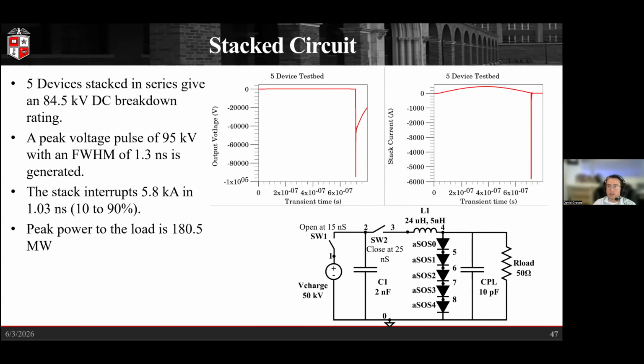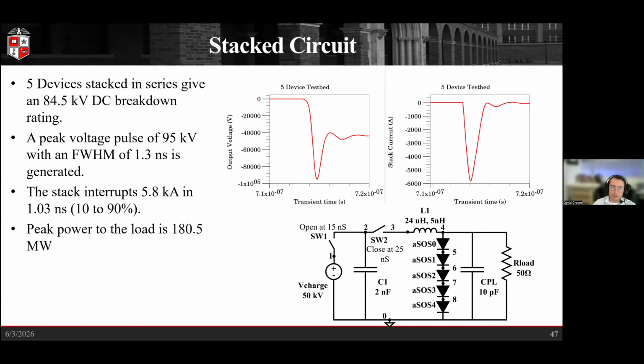So the next thing we want to do is stack these devices up. So if we stack 5 of them up in series, we have an 85 kV breakdown in DC. And if we charge with 50 kV, optimize some of the L's and C values here, we can get a system that produces a 95 kV pulse with a full width half max of 1.3 nanoseconds. And that stack is able to interrupt 5.8 kiloamps in just over 1 nanosecond. And so this stack allows us to deliver 180 megawatts to the load. Just zooming in to see the peaks.